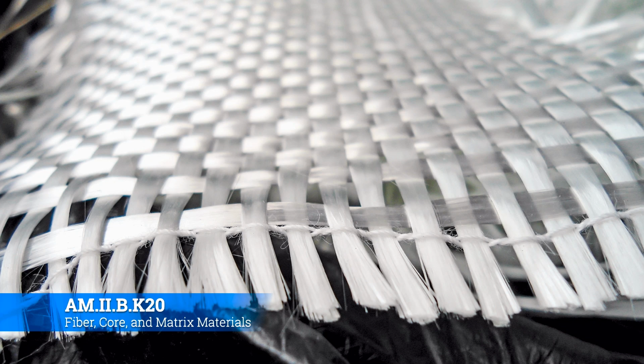They built a fiberglass hull and then filled it full of what was effectively expanding foam. And the thinking was that it was so buoyant that if it got hit by a torpedo, the torpedo would just pass through it, and the boat could just keep on trucking along. And that actually happened a few times. Because the torpedo didn't hit anything metal, it didn't detonate.